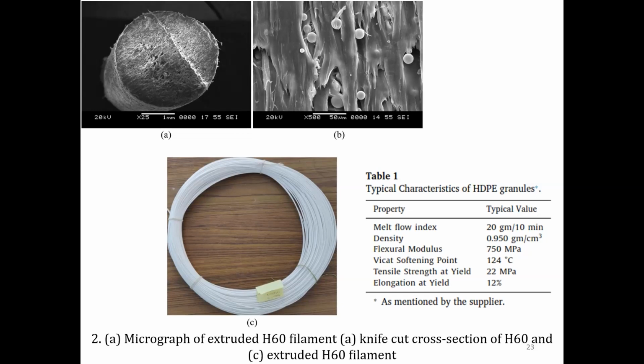So what you see in figure 2A is a circular cross-section of an extruded H60 filament, and you are able to see some mark here, right? This mark is because this filament could not be freeze fractured. What do I mean by freeze fracture? You put the material in liquid nitrogen for a day or two; we kept it for a week, but still we could not fracture it in a brittle manner, because we wanted to see the microstructure, or the morphology, here. So ultimately we took a knife, and this is the knife mark.